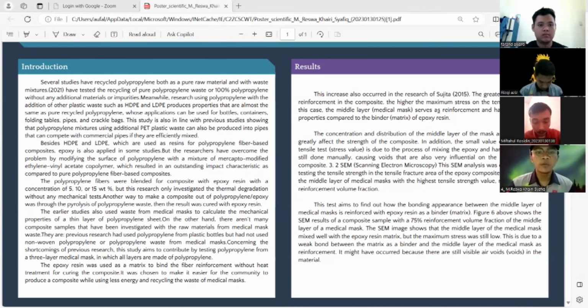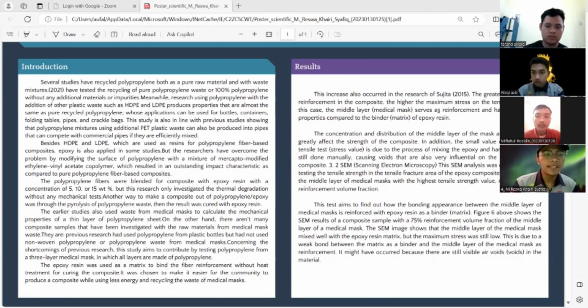This study is also in line with previous studies showing that a polypropylene mixture using additional PET plastic waste can also be made into pipes that can compete with commercial pipes if they are efficiently mixed. Besides HDPE and LDPE, which are used as resin for polypropylene fiber, epoxy composite is also applied in some studies, but the researchers have overcome the problem by modifying the surface of polypropylene with a mixture of mercaptan-modified ethylene vinyl acetate copolymer, which results in an outstanding impact characteristic as compared to pure polypropylene fiber-based composites.